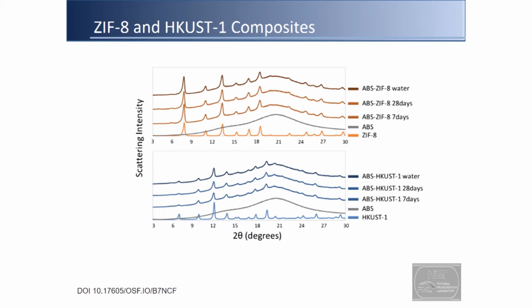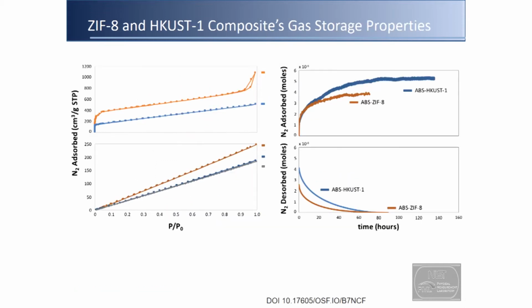Water hasn't diffused through and decomposed your crystals, so that's good news. We have also done SEM, DSC, and IR characterization, so it's all fine. What we have done up to now is measure the nitrogen uptake for these, and you can see here, for different blends between ZIF8 and HKUST-1, the different porosities and surface areas for different plastics. You can also see that the kinetics for loading the different gases are different.